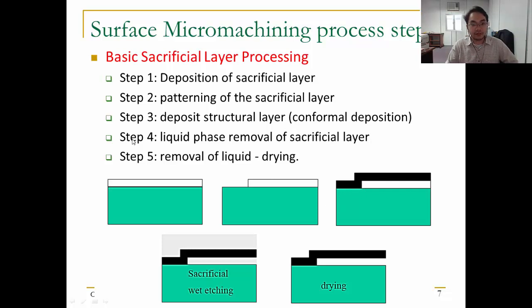After that, step number four is the liquid phase removal of the sacrificial layer. Here we can imagine that we are etching away the sacrificial layer. This can be done by either using etchant or using solvent if we are using an organic sacrificial layer. After that, step number five is the removal of liquid and drying.